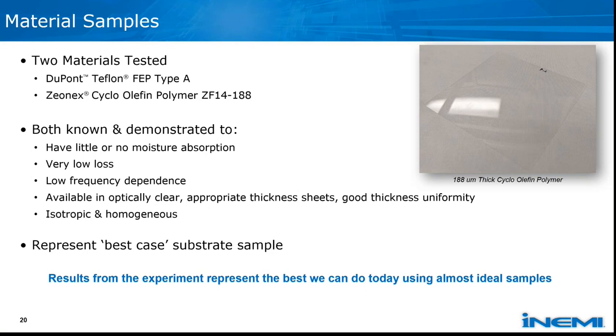So these materials were known, again, to have very little loss, very low moisture absorption. The expectation is that they have very low frequency dependence, and that was nice because we have methods that span everywhere from 10 gigahertz to over 100, and we didn't want to have a lot of frequency dependence that would confuse the data sets. These are available in optically clear sheets, and that's important because it gives you some guarantee is not the right word, but some confidence that the material surface properties are good.